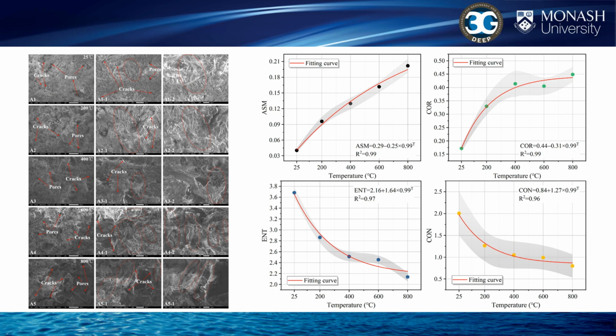The elevated density of fatigue cracks in the grain causes the formation of the compressive crushed zone, resulting in the growth of macroscopic cracks nearly perpendicular to the stress wave direction. Additionally, temperature exerts a positive effect on the ASM and COR of the grayscale co-occurrence matrix in the SEM image, yet a negative effect on the ENT and CON.